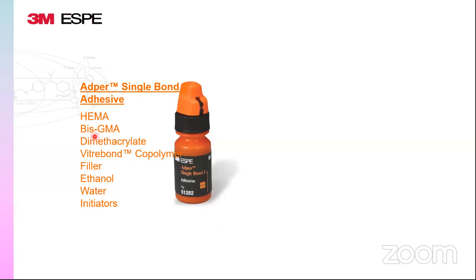So this typically would have your resins and your filler particles. It would have a carrier, a solvent like ethanol and water. Especially in this particular bond, there are two things to note. There's something called Vitrebond copolymer, and the solvent is ethanol. Vitrebond copolymer is a kind of copolymer which, irrespective of whether your dentin is dry or wet, works across that entire spectrum. What I'm trying to say is, if you have inadvertently over dried the tooth, not to worry. Even if the collagen fibers have collapsed, this Vitrebond copolymer takes care of it. Re-wetting happens, and you don't have to worry about not getting a hybrid layer.